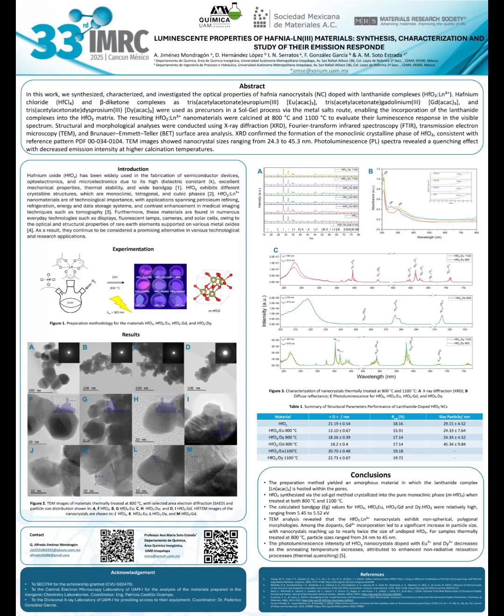Conclusions. To summarize, monoclinic HfO2 nanocrystals doped with Eu, Gd, and Dy were successfully synthesized using a sol-gel method. The particle and crystal sizes increased with thermal treatment, especially in the doped system. Diffuse reflectance data confirmed large band gap values, while photoluminescence analysis revealed decreased emission intensity at higher calcination temperatures, primarily for Eu and Dy. These results suggest that dopant type, thermal treatment and synthesis route significantly influence the optical performance of lanthanide-doped HfO2 materials.